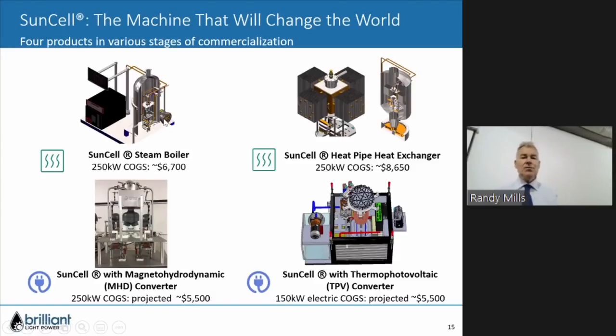So SunCell is a source of power, and then there's different components that go onto that to harness that power. Particularly the SunCell has a molten metal injector. It has this fuel processing system on the top, which is a glow discharge. And the reason being is we've run black body radiator emitting SunCells that run at very, very high temperature. But when you put them in water and you have the walls at cold water temperature, then it won't work. And the reason is because it doesn't get hot enough. To solve that problem, I invented a glow discharge reactant preprocessor.